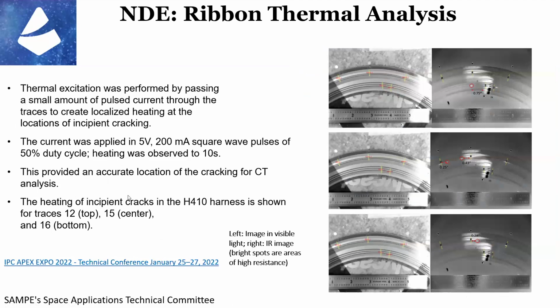So what we ended up doing with the IR is we actually were able to get very small 5-volt pulses, because I didn't want to damage the harness itself, into the wiring of the harness itself. And where there was a little bit of incipient cracking, because these wires weren't broke, they were just not transmitting the way they were supposed to, I was able to get it to heat up just a little bit, and I could map that with our IR camera and pick out all these little areas on the different traces, so that I could then cut them out to do something a little bit more high resolution.